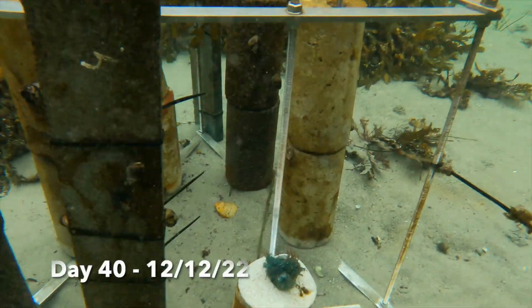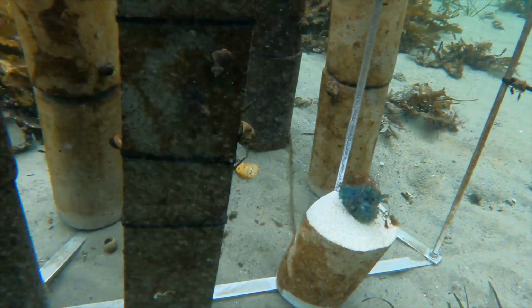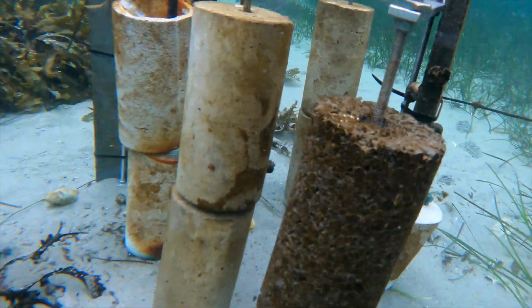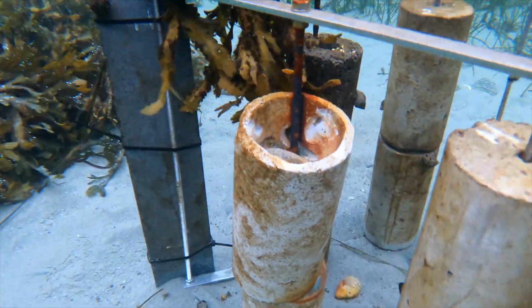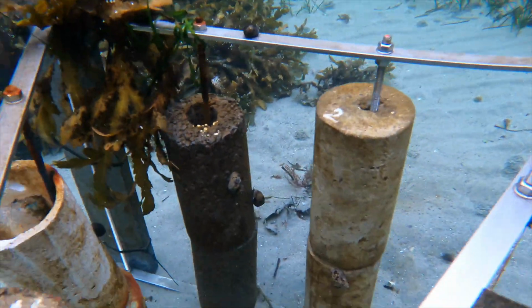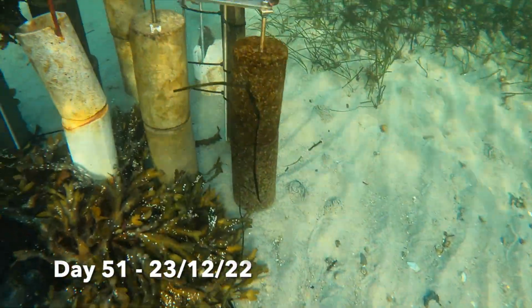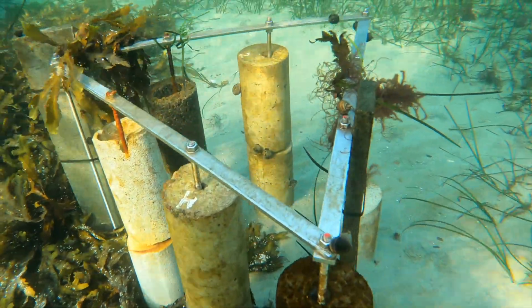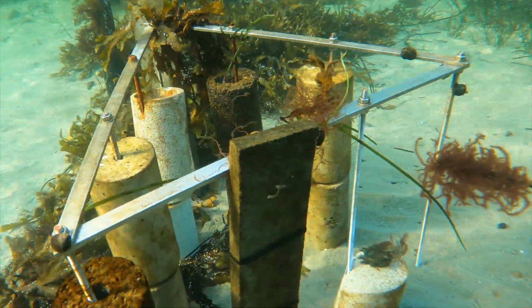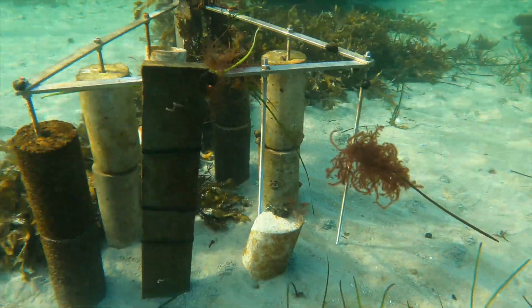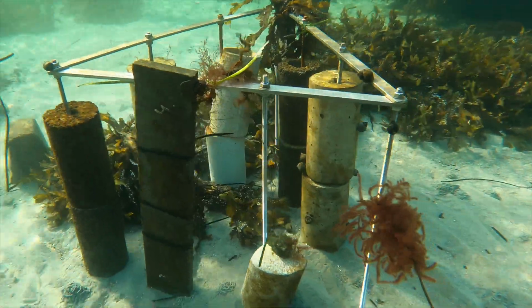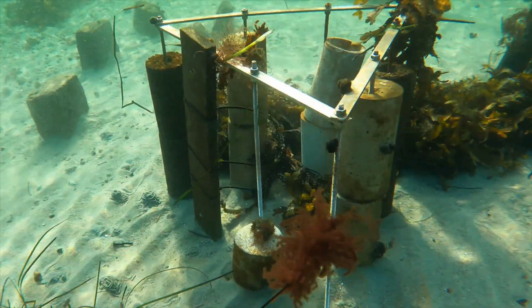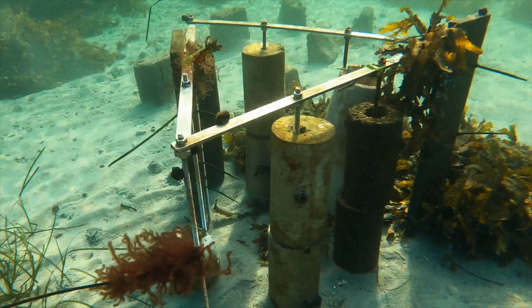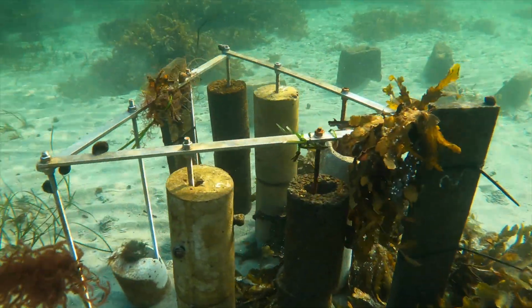One of the test materials, the AAC, actually did seem to outperform the others in ecological value, as it had more discoloration and algal growth on the surface area. However, the AAC was also the sample most affected by the wave action, moving the specimen and grinding them away from the inside. These durability issues were of course worrisome, but were concluded to be caused by the rack that wouldn't exist in an actual reef.